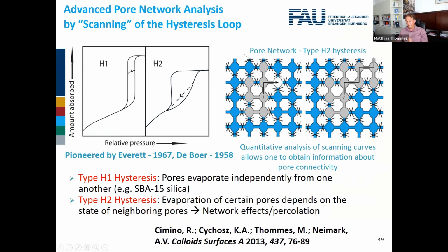This changes, of course, if you have a system which gives rise to this percolation transition, because usually you would have this percolation, pore blocking driven evaporation when none of the fluid here has access to the outer world, only through this narrow neck. But if you fill these particles only to a certain extent, then you might have neck pathways open to the interior of the particle, and now liquid can evaporate without blocking.